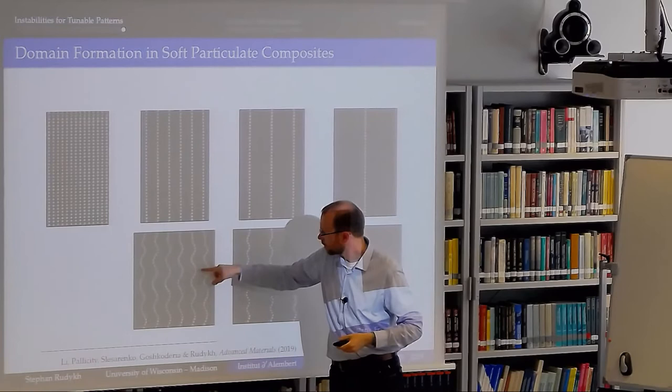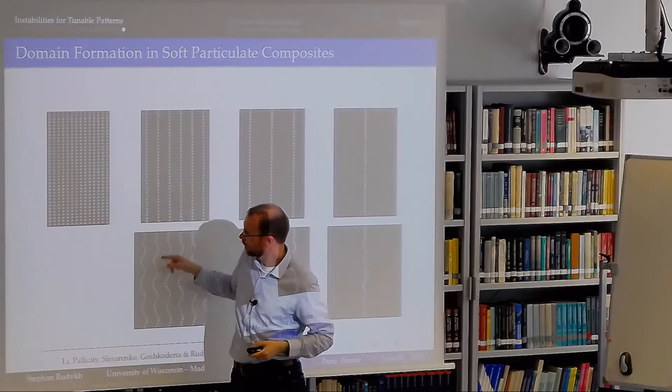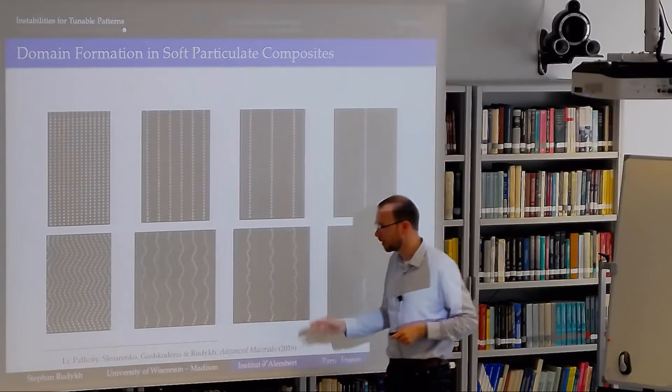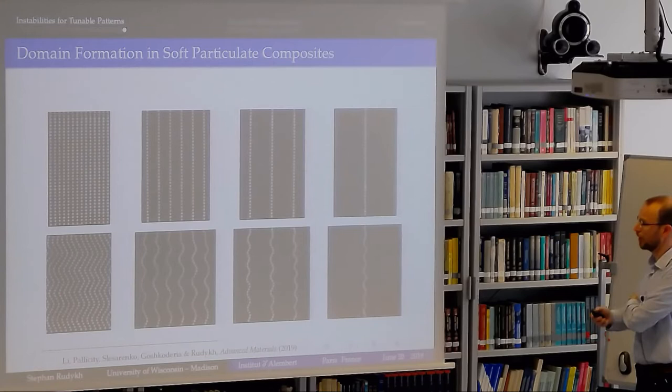Now, if we bring these columns of inclusions close to each other, they cannot really form this wavy pattern, and they become sort of frustrated, and they need to find a new way to rearrange. And so that's the transition to that domain or twinning type of instability. All right, so